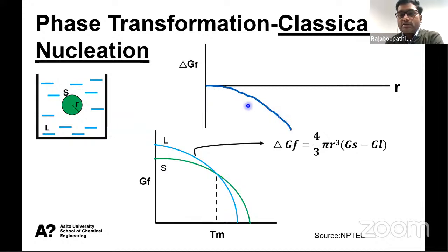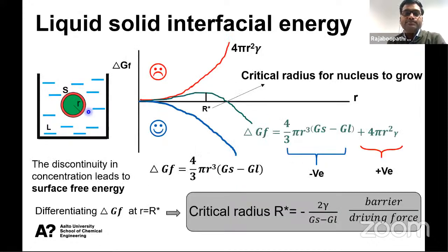So this Gibbs free energy decrease is equal to 4/3 pi r cubed times (Gs minus Gl). Gs is the Gibbs free energy of the solid and Gl is the Gibbs free energy of the liquid. Here I'm assuming this nucleation cluster is a sphere with radius r, so I'm using 4/3 pi r cubed. If it is a cube or a rectangle, you can use a different expression according to the size of the nucleation cluster.